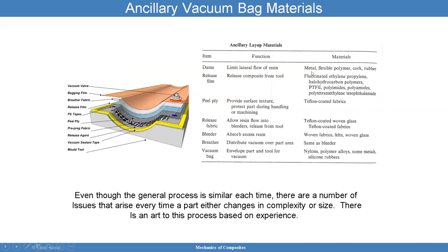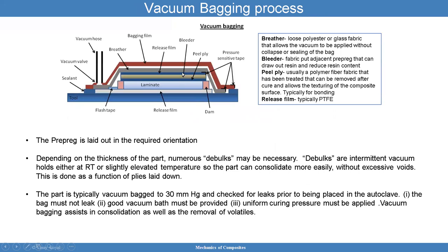A typical dam could be metal, flexible polymer, cork, or rubber. The release film allows release of the composite from the tool. We talked about it, otherwise it gets stuck. And these are the kinds of materials you could use. The peel ply provides surface texture and protects the parts during handling or machining. These tend to be Teflon coated fabrics. You have the release fabric, which allows resin flow into the bleeders and releases from the tool. And that can be Teflon coated woven glass, Teflon coated fabrics. I already discussed the bleeder. It absorbs excess resin, and I showed it here. It's usually adjacent to the composite.